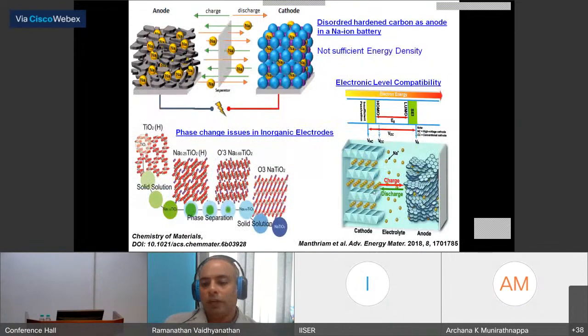And if you look into literature, what are the approaches being used? People use hard carbon as the anode and combine it with sodium cobaltate. This is one of the commercial batteries. But the problem is you don't have a major attraction for sodium here. So it is a little sluggish in how quickly you can sodiate and desodiate. And also the number of active sites for sodium is limited because at best you can form sodium C6 or sodium C8. And so the energy density is limited, even theoretically.